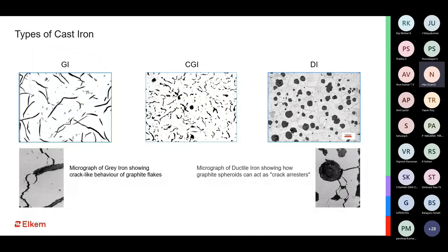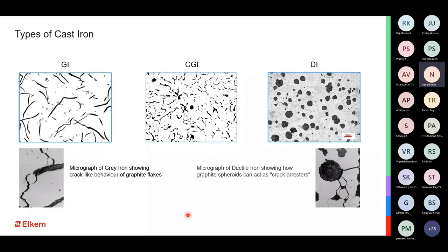Just to tell you why gray iron is different from ductile iron, we can see it from these microstructures. If you look at these three microstructures, the one on the left of your screen is gray iron, which can clearly be seen by looking at the graphite flakes. The graphite is in the form of flakes with very sharp ends, and these sharp ends of the flake can act as a crack initiator. So the crack initiation happens on these pointed graphite flake ends, which results in a much lower mechanical strength, or a much lower tensile strength, of the casting.